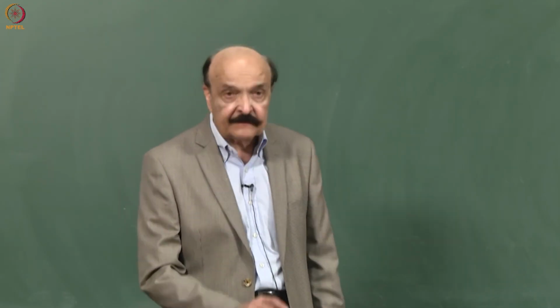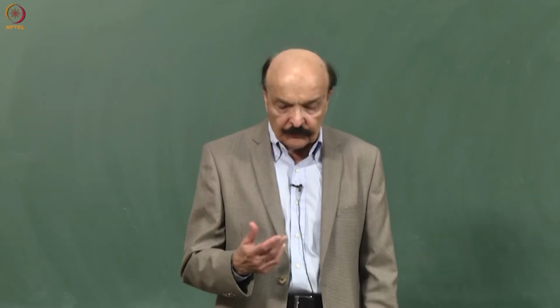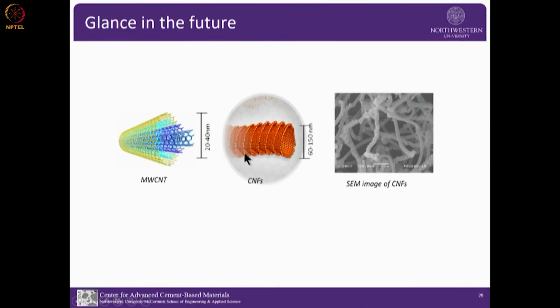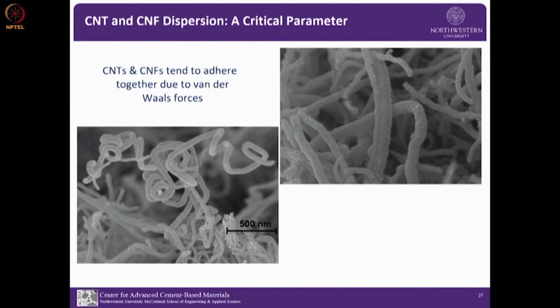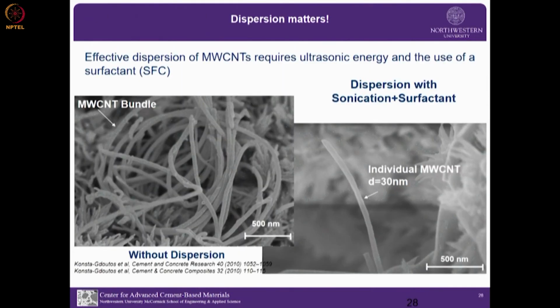So I want to show you some results of well dispersed carbon nanotube. We have also been using carbon nanofiber, which is somewhat coarser, and because of the way they are made, we have not checked it, but we think the bond could be somewhat better. Here is an example of what happens if fibers are not well dispersed: they conglomerate. When well dispersed, we have individual, in this case multi-wall, carbon nanotubes. This is with the SEM, and there is really not a very good way to find dispersion of carbon nanotube in hardened material, because you don't see them very well at nanoscale in SEM. In an aqueous solution you can, with UV spectroscopy.